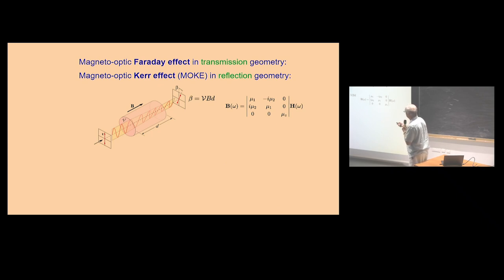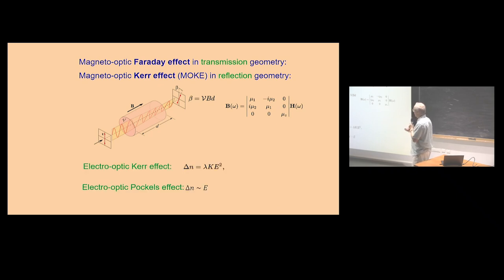Frequently people do not measure the magneto-optic Faraday effect, which is in transmission geometry, because the sample is frequently non-transparent. So they measure in reflection geometry, and in this case it is called the magneto-optic Kerr effect. But it is practically the same. You see the rotation of the optical beam polarization. Don't mix it with the electro-optic Kerr effect, which I will speak about as well.